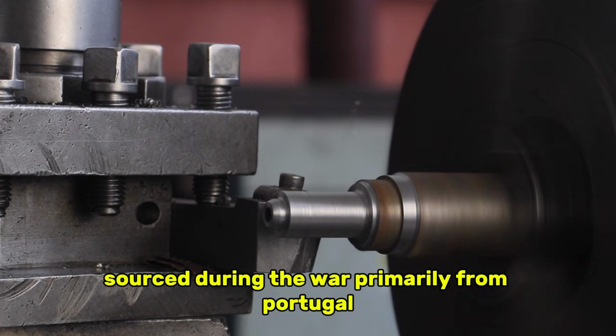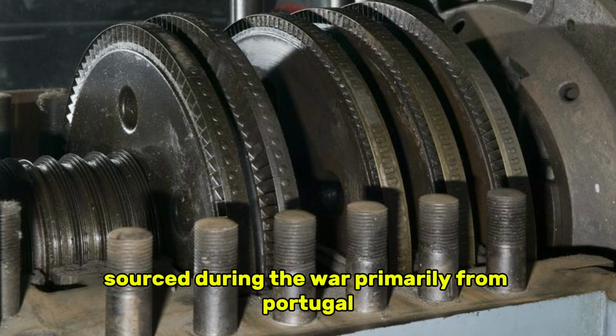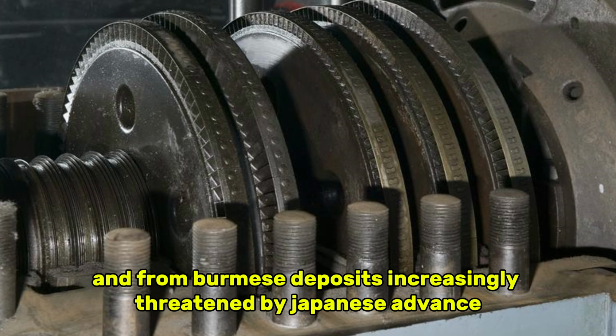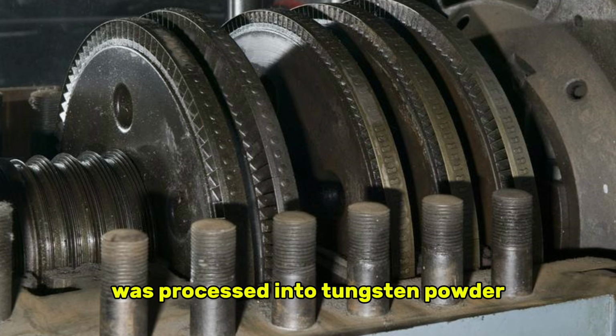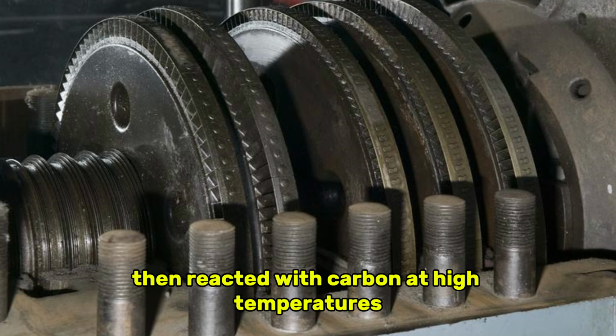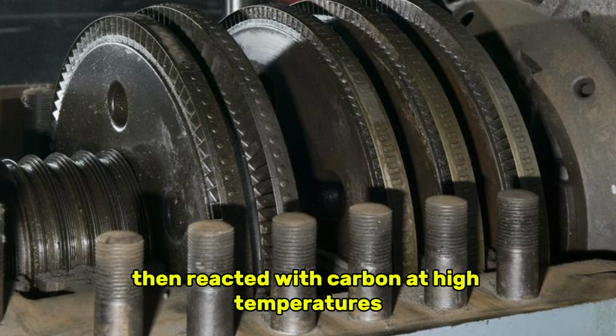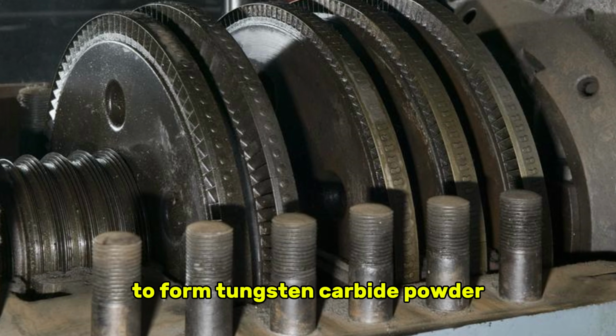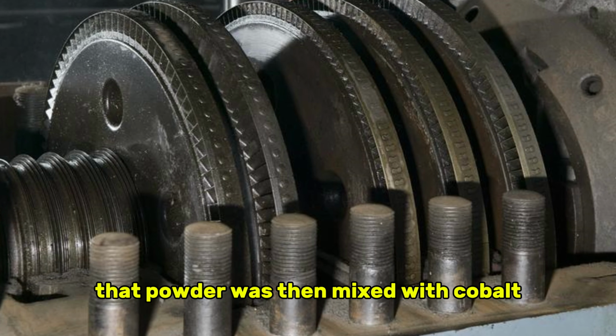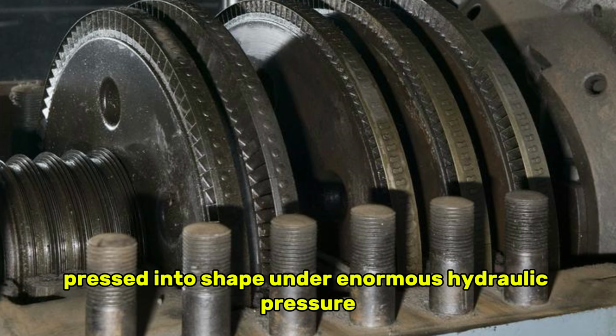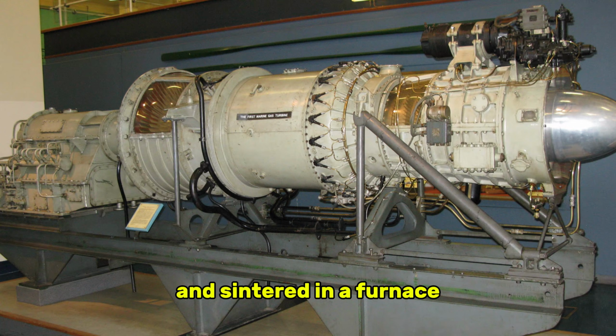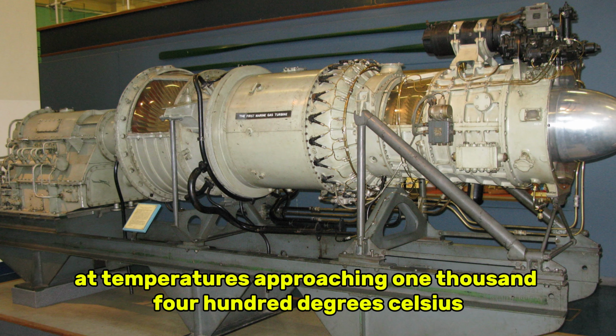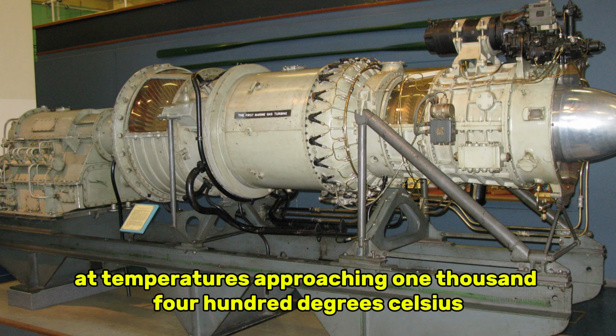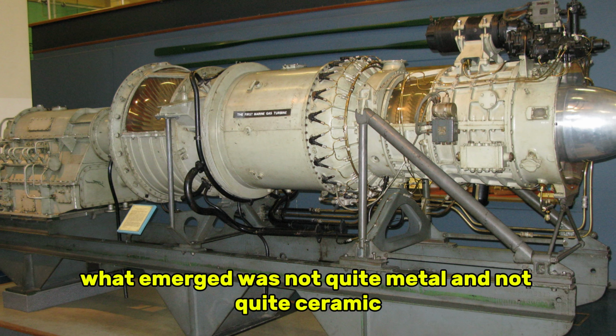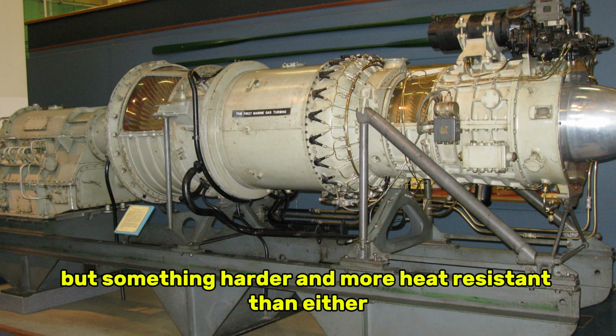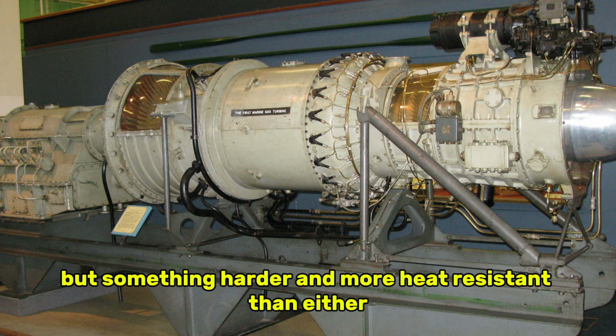Tungsten ore, sourced during the war primarily from Portugal and from Burmese deposits increasingly threatened by Japanese advance, was processed into tungsten powder, then reacted with carbon at high temperatures to form tungsten carbide powder. That powder was then mixed with cobalt, pressed into shape under enormous hydraulic pressure, and sintered in a furnace at temperatures approaching 1,400 degrees Celsius. What emerged was not quite metal and not quite ceramic, but something harder and more heat-resistant than either.